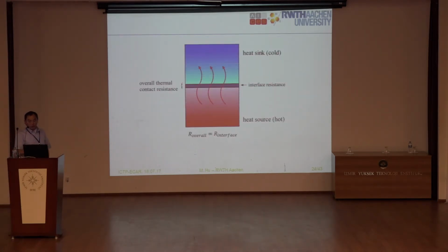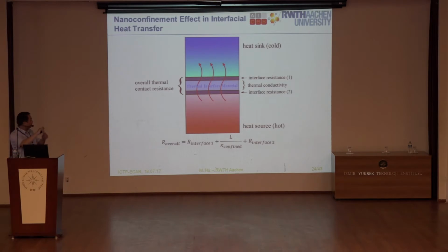So in traditional thermal transport, you have only two materials in contact, A and B, and heat is generated on one side and goes away to the other side. In this case, the thermal resistance is just the interface resistance between these two materials, right? So nowadays, with nanotechnology, you can easily fabricate nanomaterials, which we call thermal interface materials, and sandwich them in between. So the question is, is it possible to reduce the overall thermal contact resistance as well?